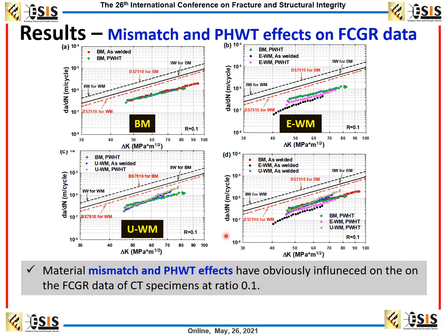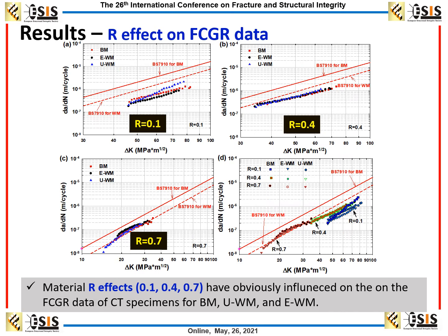So the FCGR data are summarized in this figure for these three materials. The material mismatch and the PWHT effects have an obvious influence on the FCGR data of the CT specimen and the stress ratio. Although some articles report that the R ratio is sensitive in some high strength steel materials or bainitic structure steels, the R ratio effect on the FCGR data of our study is visible, especially for the even matched weldment.